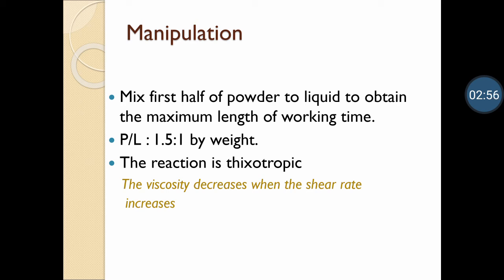We can extend the working time for the clinician's advantage by cooling the glass slab and also by refrigerating the powder. We should not refrigerate the liquid, because that causes gelation of the acid present in the liquid. So it has to be avoided.